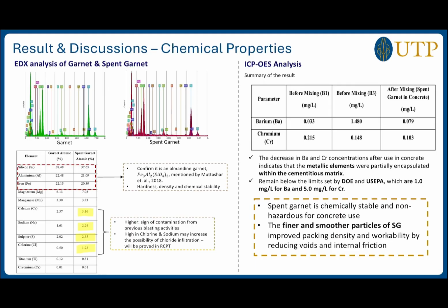And from the table here, we can see after mixing spent garnet in concrete, the concentration of barium and chromium decreased compared to before mix, showing that metallic elements were partially encapsulated within the cementitious matrix. And this value remains below the limit set by DOE and US EPA, which are 1 mg per liter for barium and 5 mg per liter for chromium. And to conclude, spent garnet is chemically stable and non-hazardous for concrete use, and the finer and smoother particles of spent garnet improve packing density and workability by reducing voids and internal friction.